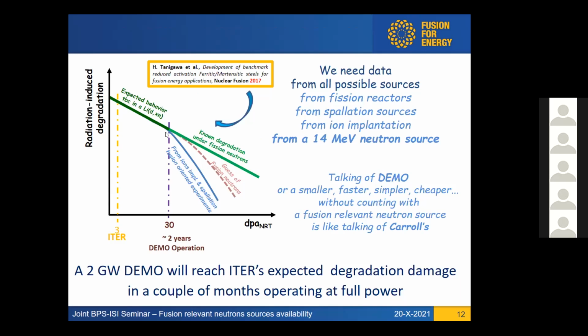So this allows us to anticipate that reduced activation ferritic martensitic steels can very nicely work, likely for 2 years with no problem, because we know already that they can hold up to 30 dPa, more or less correlated with what we have seen in fission reactors. But afterwards, we don't know. And certainly, if we want fusion power to be a commercial solution, we need to allow the reactor to work for more than 2 years without a major intervention.